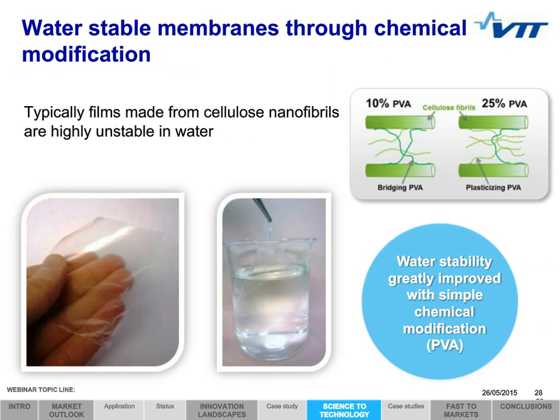Typically, cellulose nanofibril films are highly unstable in water. However, with a very small addition of polyvinyl alcohol to chemically modified cellulose nanofibrils, films that sustain their structure in water for days or even weeks can be prepared.